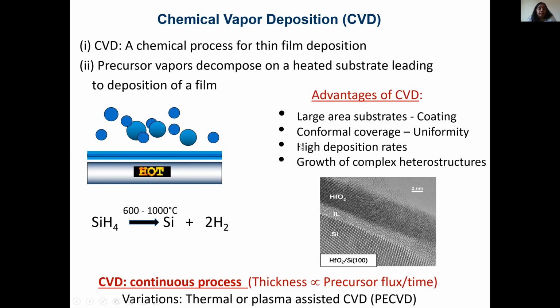The advantage of CVD compared to physical vapor deposition techniques like sputtering or evaporation or pulsed laser deposition or molecular beam epitaxy is that in CVD you can grow on very, very large area substrates. And moreover, you can conformally cover it. So suppose you have very complicated geometries, you can coat it very uniformly, even very precisely. And the deposition rate is pretty high, and you can have some complex heterostructures. That means you can have different materials stacked one over the other. So here is a cross section of a substrate and the film formed, that's hafnium oxide, just to show that the TEM image shows the nice demarcation between the substrate and the film.